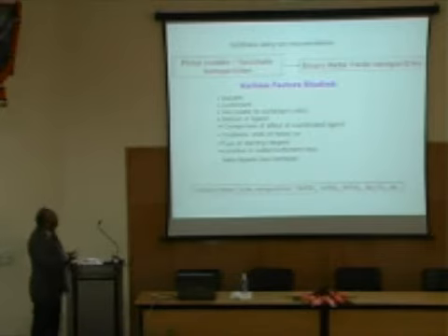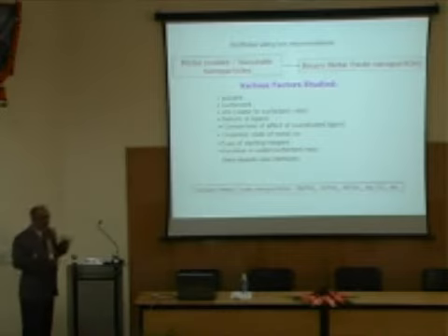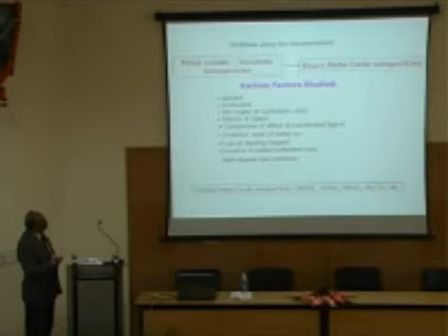And what are the parameters that we study to control the size and shape? Because our main aim is to control the size and shape of these nanostructures. So you can control the solvent, the surfactant, the amount of water you add to the surfactant, because it will control the size of those. We call them nanoreactors because the reaction is taking place in those small volumes of the structures made by the surfactants, and several other things.